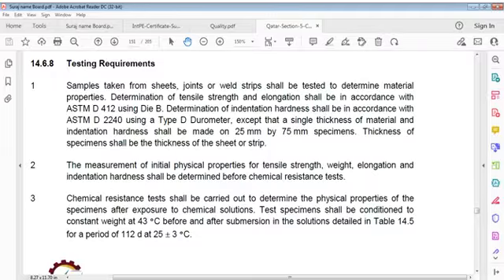Determination of indentation hardness shall be in accordance with ASTM D2240 using a type D durometer, except that a single thickness of material and indentation hardness shall be made on a 25 mm by 75 mm specimen. Thickness of specimen shall be thickness of sheet or strip.